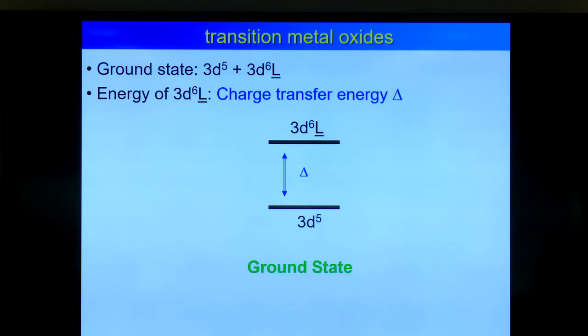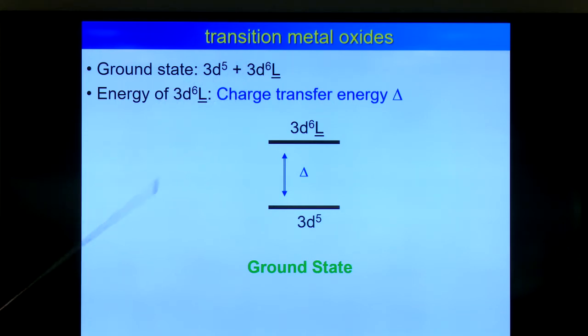The description we use for transition metal oxides is to use different configurations. So we start off with the ionic configuration. We say manganese 2+ is 3d5, and then we mix with a second configuration where we move an electron from the oxygen 2p valence band to the 3d band. So then it's 3d6 L-bar, the ligand hole, and this has a certain excitation energy. It's not exactly the band gap, because it's modified by correlation effects, but it is the charge transfer energy related to that state.